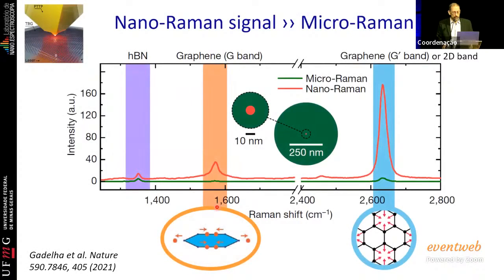Okay, and again, what this antenna does is, when you approach the antenna to the surface, before you had an illumination area that is represented by this green circle here, and then you measure a Raman spectrum that is here, okay? And then when you approach the antenna, you will enhance the field very strongly only at the apex of the antenna. So in a very small place here that is in the order of 10 nanometers. And because the antenna is very efficient, the signal gets highly enhanced. So the signal coming from all the illuminated area becomes negligible with respect to the signal that you are measuring locally at this very specific point.